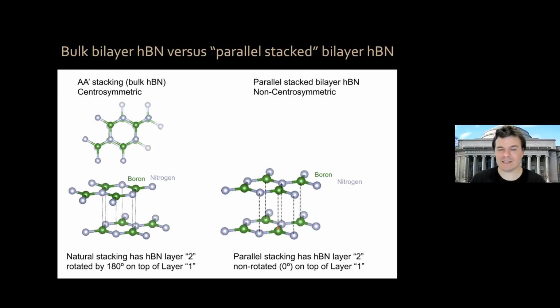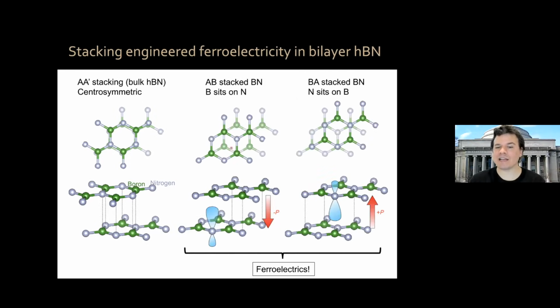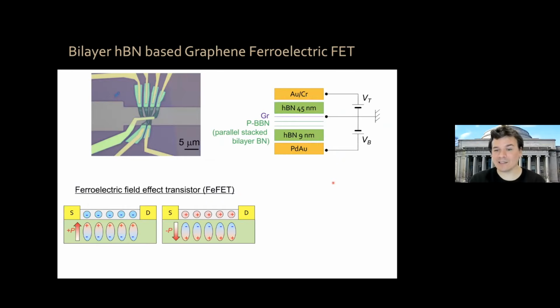So what it does instead is it shifts laterally such that it reaches an arrangement which is of AB stacking, meaning boron sits on top of nitrogen, or alternatively, BA stacking, meaning nitrogen sits on top of boron. And it turns out, if you look at this and you calculate this structure, either of these structures has a permanent electric dipole moment. In fact, if you can switch between the two structures, then you would have a ferroelectric switching, okay? And indeed, that's what we did, okay? So we made devices where we have a parallel stacked boron nitride bilayer, okay?